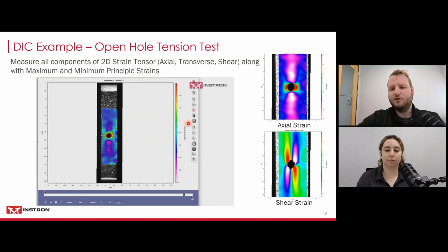So when you load your specimen, the video extensometer will record the images during the test, and it's an adjustable rate, which you can set how many pictures to take per second. And the DIC software will then compare the images to each other and visualize the strain field for you. So you can now add a digital extensometer, for example, or a digital strain gauge to your specimen. And we'll go over some interesting examples for this in the later part of the presentation.